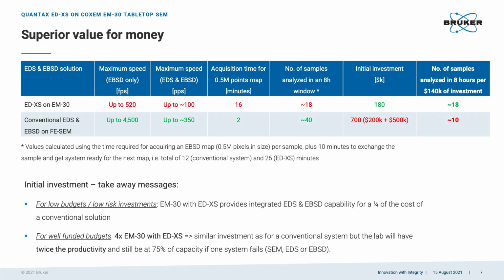So practically the takeaway messages are for low budgets or organizations which may not be willing to take high investment risks, then they could buy the EM30 with ED-XS, and that would provide them an integrated EDS EBSD capability at 1/4 the cost of a conventional solution. For those which are well funded, for the same money, they could get 4 EM30 tabletops with ED-XS, and that would give them twice the productivity. And in case one system fails, they will still be at 75% of capacity. While if you have a conventional system and in the FE-SEM it's offline or the EBSD detector it's offline, then you're at 0 capacity. You're on downtime.